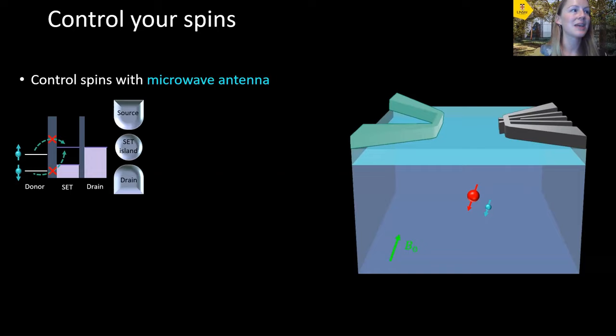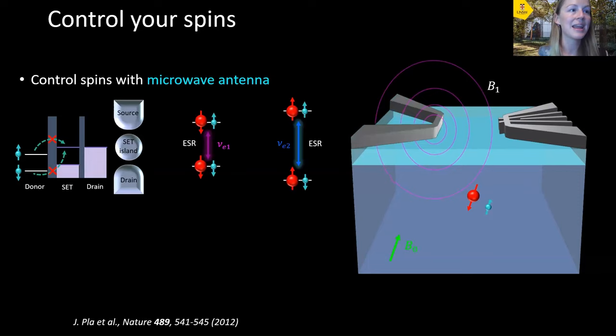And then we use our microwave antenna to apply an oscillating signal, and we obtain two electron spin resonance peaks corresponding to the nuclear spin of the donor being either spin down or spin up. And this flips the spin of the electron in both cases, because the frequency of the microwaves that we apply matches the energy splitting between our electron in the spin down and spin up states.